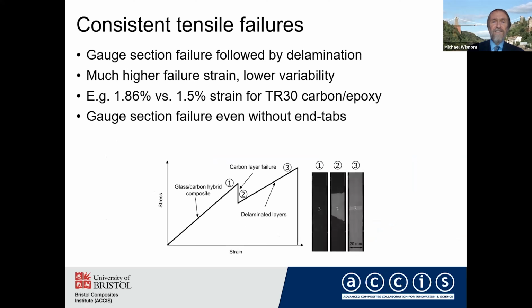We get consistent failure, and we get the failure in the middle. You can see the specimen here, that it's failed in the middle. When the carbon fails, it then delaminates, and you can see the delamination spreading, and therefore the specimen changes color. And so we can see that we've got a real gauge section failure. And actually, we don't even have to put tabs on these. We can put them straight into the grips of the test machine. And we get significantly higher failure strain and lower variability.